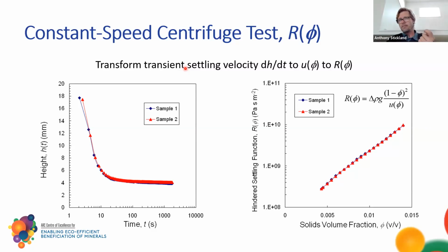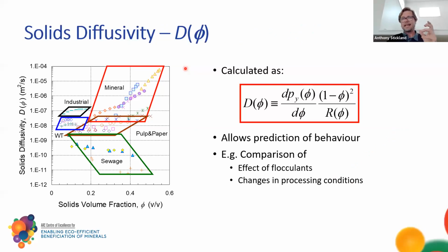If I take my governing equation, I can typically reformulate it, and it turns out to look like a second order partial differential equation that looks like a diffusion equation. And the diffusivity is some combination of that compressibility and permeability. That diffusivity is telling me, if I have a change in concentration because of some pressure that I'm applying, for example, how quickly does that concentration propagate through the body? And so it's a really useful parameter to compare different materials.